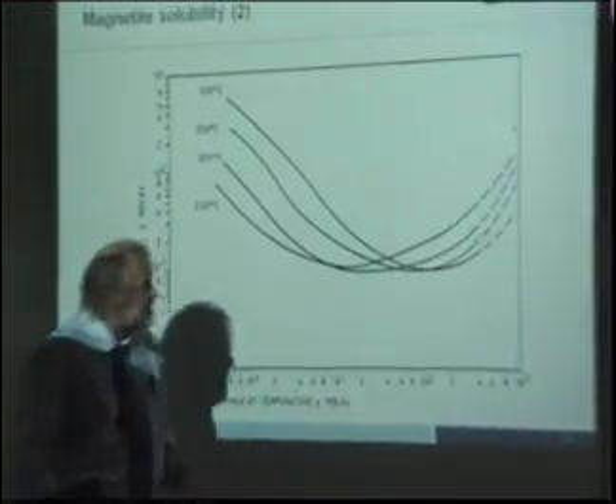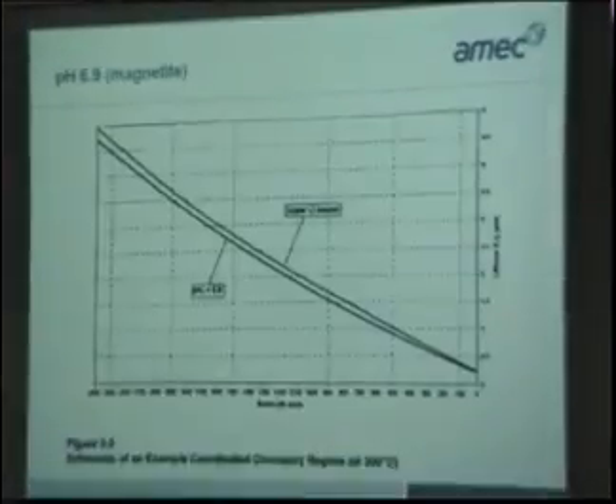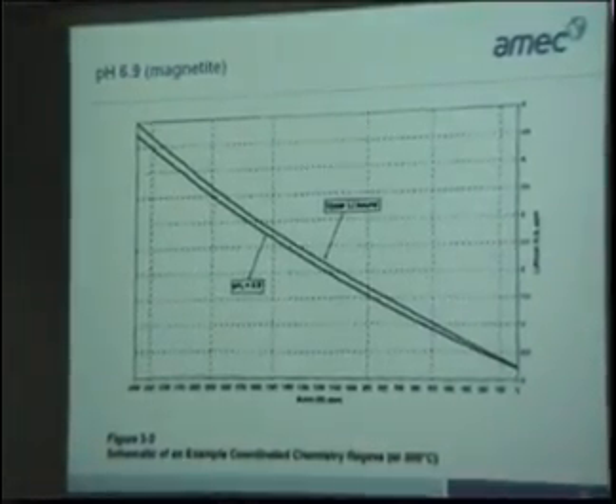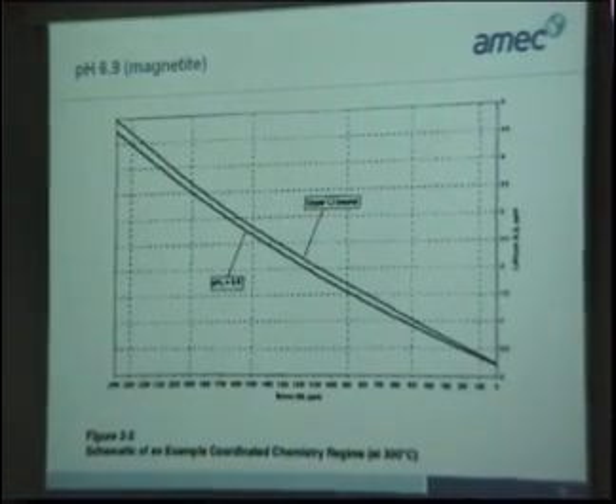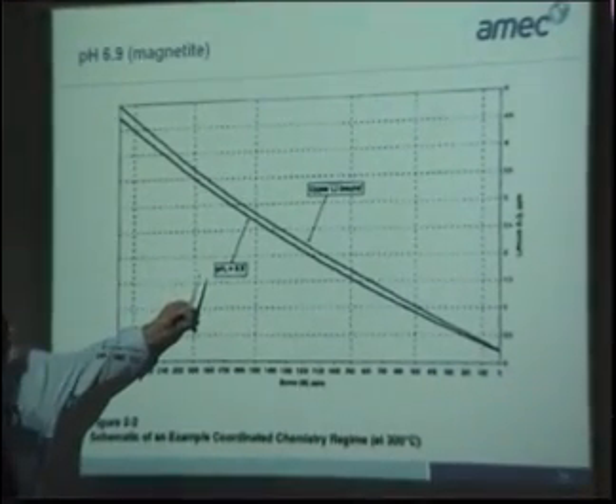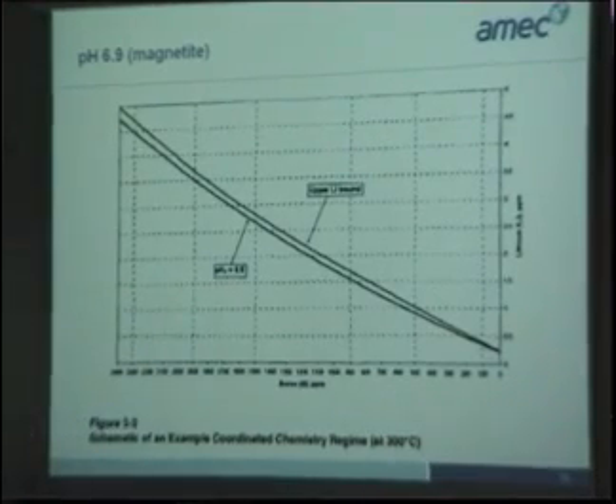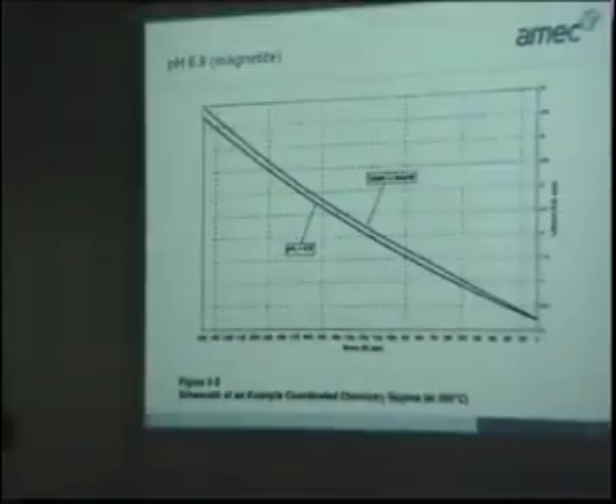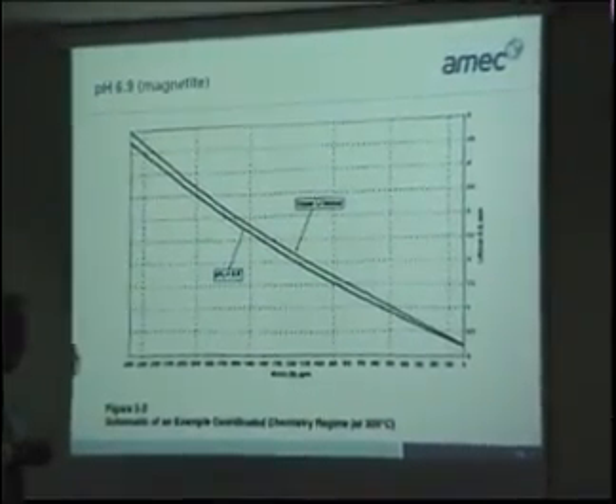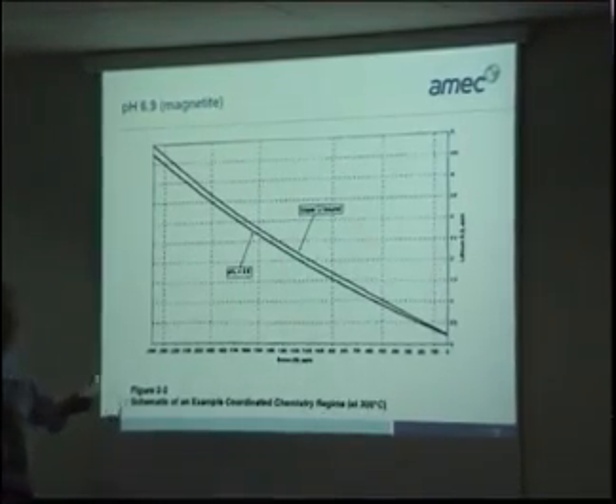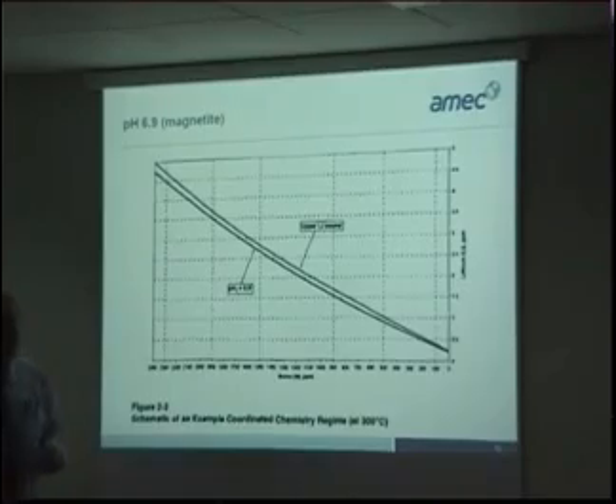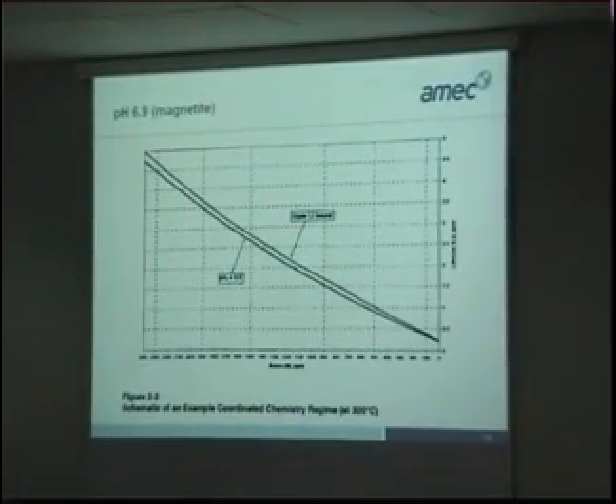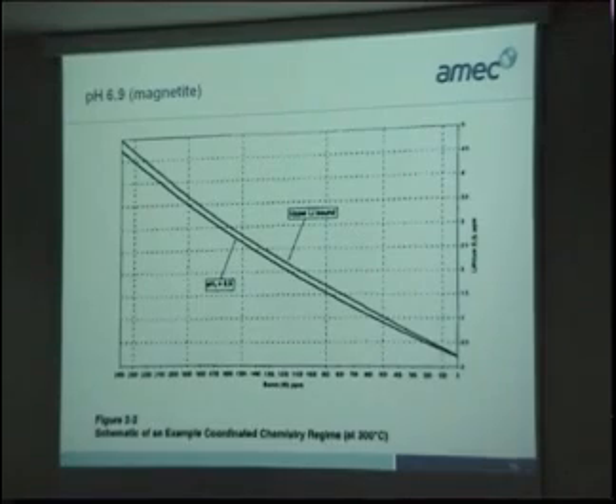So we're looking for a pH operating in this region, and based on magnetite data, this is now a little bit historical, we find that the pH is about 6.9. Just bear in mind that pH of 6.9 is at 300 centigrade. Everything's measured relative to 300 centigrade because that's an average operating temperature. In the early operating days, well, not so early actually, they didn't bother with pH control and they ran into all sorts of problems. These were the old reactors in the States.